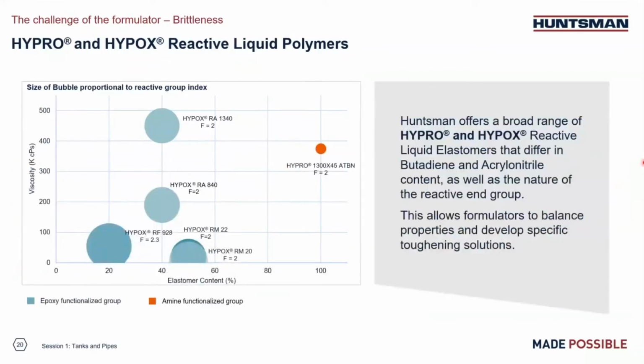So we have a broad range of tougheners you can choose from, some under the HYPRO and some under the HYPOX brand name. For HYPRO, for example, which is amine terminated, you can add this to the curing agent side, because for a lot of heavy duty formulations, the curing agent usually has lower viscosity than the epoxy resin side. By adding the toughener into the curing agent side, we can minimize the impact on the overall system viscosity.